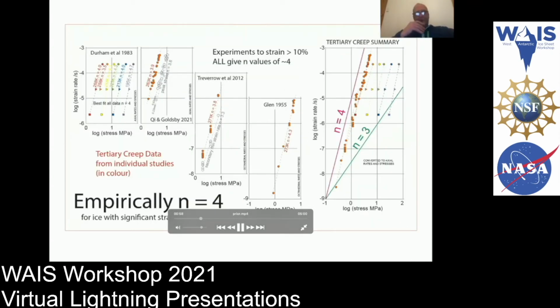The empirical base for n equals 4 is really strong. Every experiment which has enough data to define a tertiary creep n value has a value of 4, or in some cases rather larger than 4. Okay, so there's constant load experiments, constant rate experiments, a whole range of temperatures. Durham et al. 1983 defines a flow law for ice, which has an n equals 4 value.